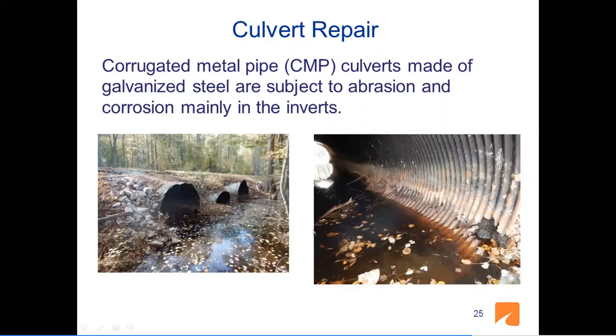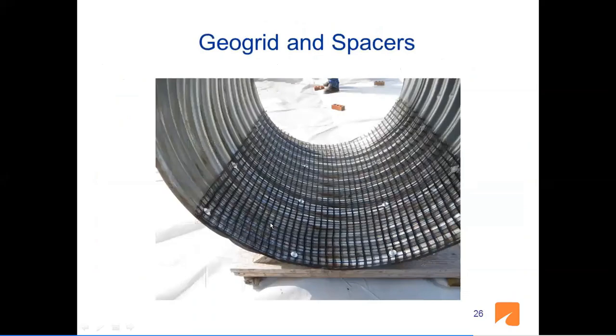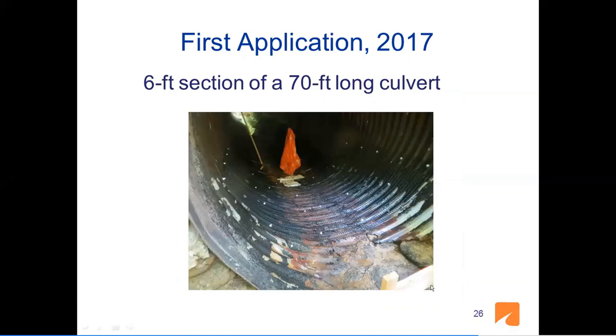These corrugated metal pipes, metal culverts, are made of galvanized steel, and they are subject to abrasion and corrosion, mainly in the invert, at the bottoms of these culverts. And what we do is we put a geogrid, biaxial geogrid, it can be PVA or it can be polypropylene material. And we also attach this to the metal culvert through screws with spacers. These spacers are important because we are trying to make very thin layers, less than 1 inch over the corrugations because of environmental concerns. Very thin concrete layer there at the bottom of these inverts.